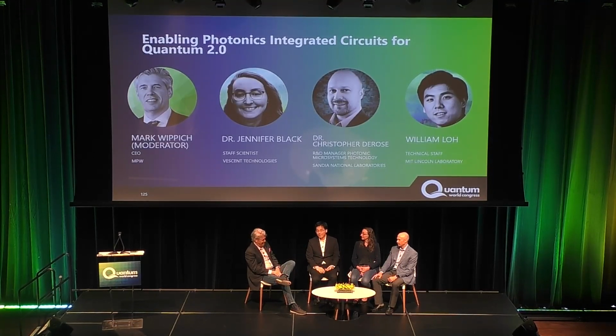It gets harder. Lithium niobate is the opposite. I mean, it's hard, but there's actually a lot of benefits. It's an understatement. It's actually very hard, but when you confine light down to small volumes, all of a sudden the intensity just blows up. And things like nonlinear optics, second harmonic generation, all become accessible with milliwatts of power now. And also, you can put your electrodes very close, and so modulator V-pi's go down. So those are the two topics I would pick.